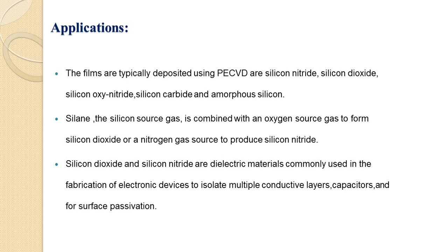Silicon dioxide can be deposited using a combination of silicon precursor gases like dichlorosilane or silane and oxygen precursors such as oxygen and nitrous oxide, typically at pressures from a few millitorr to a few torr. Plasma deposited silicon nitride, formed from silane and ammonia or nitrogen, is also widely used, although it is important to note that it is not possible to deposit a pure nitride in this fashion. Plasma nitrides always contain a large amount of hydrogen which can be bonded to silicon or nitrogen.